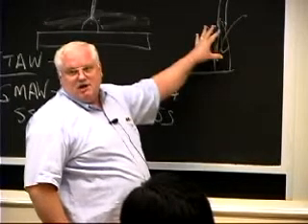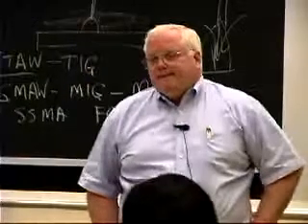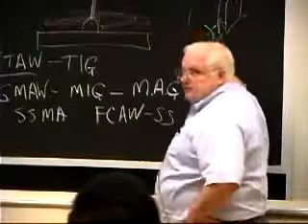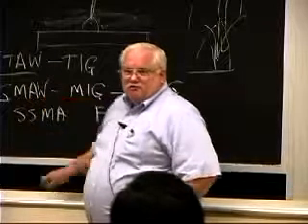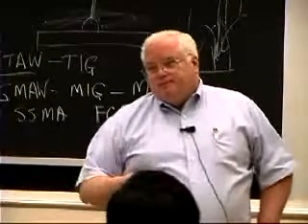If that air has a lot of moisture, you're going to end up forming monatomic hydrogen that will get into the steel. So no matter what, unless you shield with an inert gas, you can't keep it out. If I go to gas metal arc and I'm using dry argon, there's no moisture there, so that's not the problem. A lot of what we do in the shipyard now is gas metal arc, but stick electrode still has the problem.